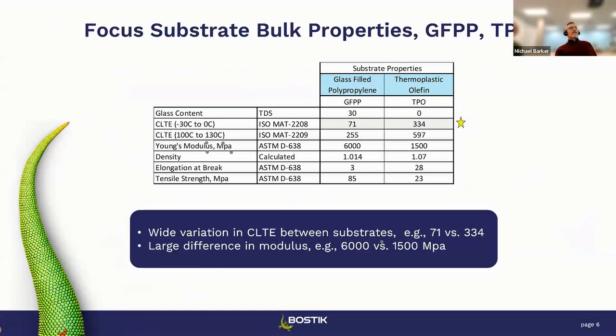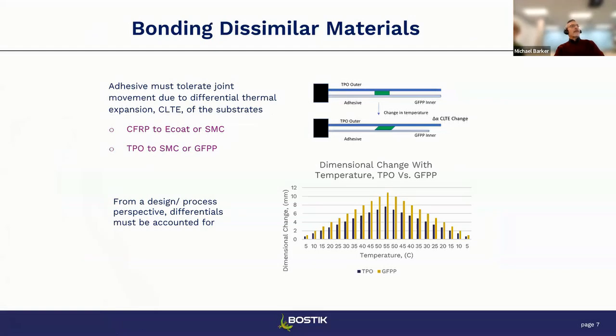Right now we have listed a table here of the two different substrates that I'm going to talk about. There's a glass-filled polypropylene and the thermoplastic olefin. And really the things that I wanted to point out here, we've got the star on it here, and we're talking with the glass-filled polypropylene, a CLTE of about 71, and then without the glass, a CLTE of about 334. And so what this is doing is it's setting up a huge differential with the expansion and contraction of the two different substrates. And what happens when that occurs?